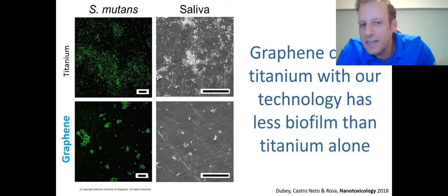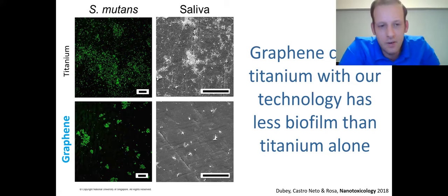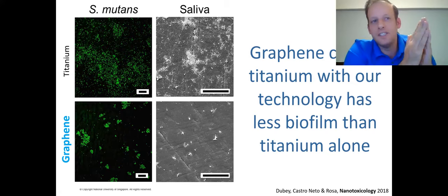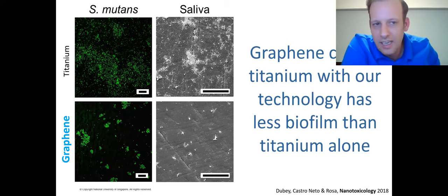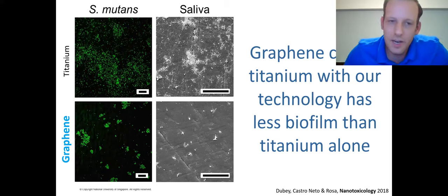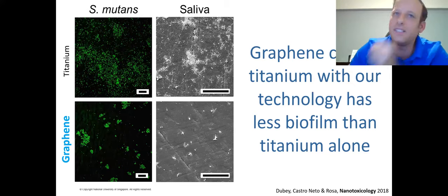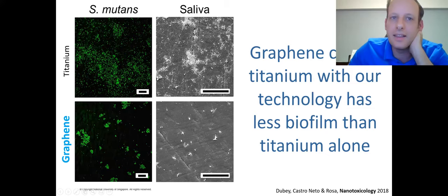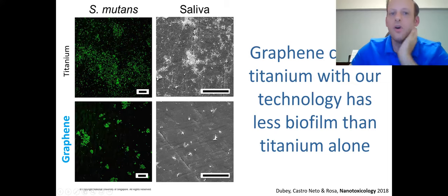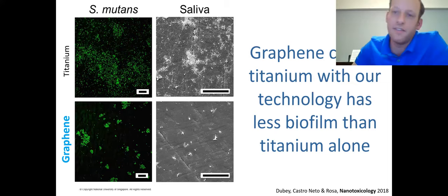What was more exciting about that is that we just spat on our samples. And you know, the mouth is the home for more than 700 species of bacteria. So when we spit on the sample, we are not putting one type of bacteria there. We are putting everything we have inside the mouth. And then what we see, if we compare these two images here, is that rarely a biofilm forms on graphene, even though we have used whole saliva.